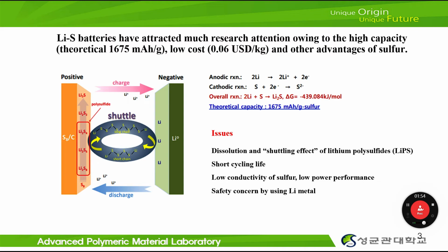But during the cycling, there are some soluble lithium polysulfides, and they can dissolve in the electrolyte solvent. So the dissolution and the shuttling effect of those lithium polysulfides cause the loss of the sulfur active materials in the cathode side, and the low conductivity of the sulfur brings the inferior rate performance of the lithium-sulfur batteries.